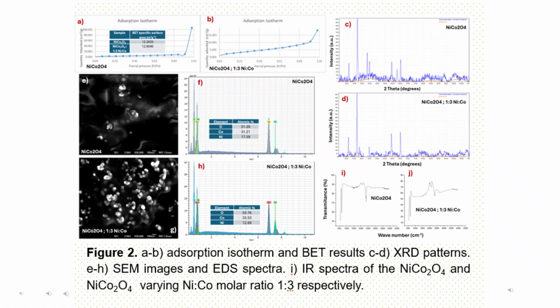XRD patterns confirm the formation of a spinel in both samples. The characteristic peaks at 2 theta at 31, 37, 44, 59, and 65 were observed, and this proved the presence of a spinel. SEM images show the formation of nanostructure aggregates with a size in the range of tens of nanometers approximately. The morphology was relatively uniform in both samples, and the samples with a nickel cobalt molar ratio of 1 to 3 show the formation of smaller and more interconnected particles.